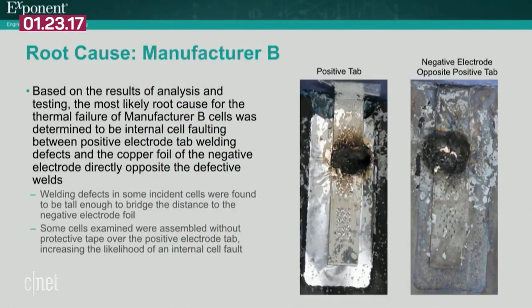cells. Exponent's findings related to the thermal failures of cells from manufacturer B showed that manufacturing defects on the welds of the positive tab were able to bridge the space between the positive tab and the neighboring negative electrode, resulting in cell faulting and, in some instances, thermal runaway. The weld defects were related to the height of the features left behind by the ultrasonic welder used to attach the positive tab to the positive electrode current collector.